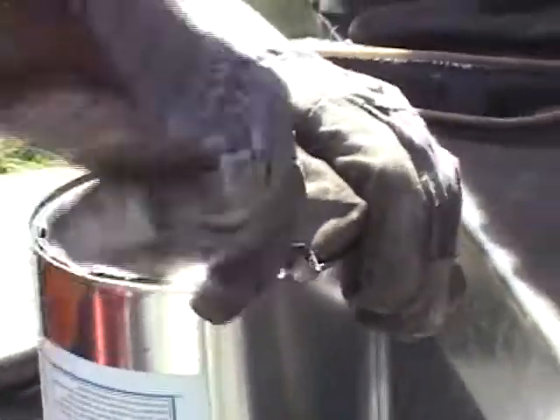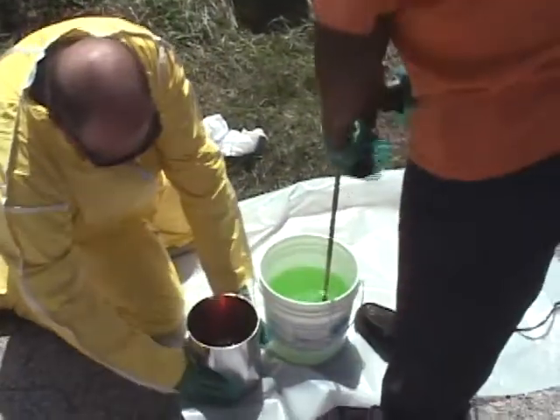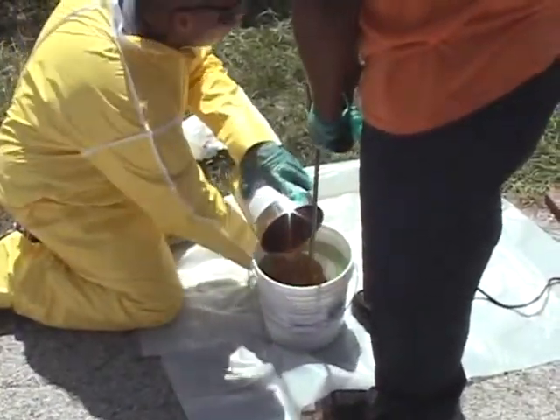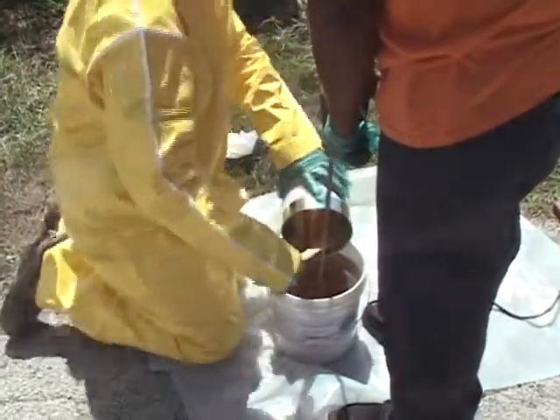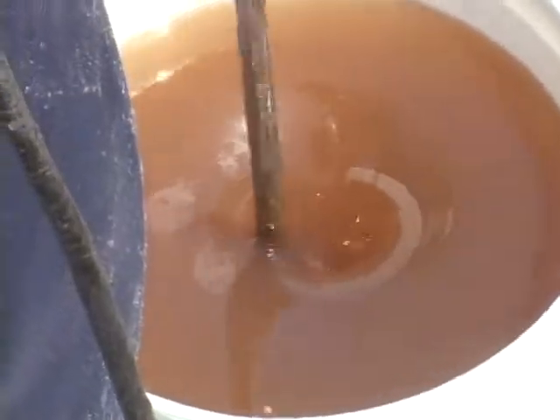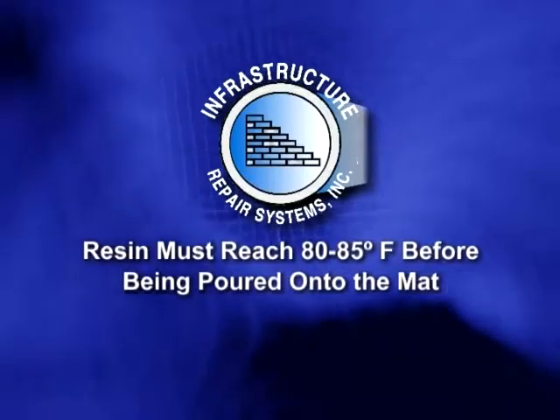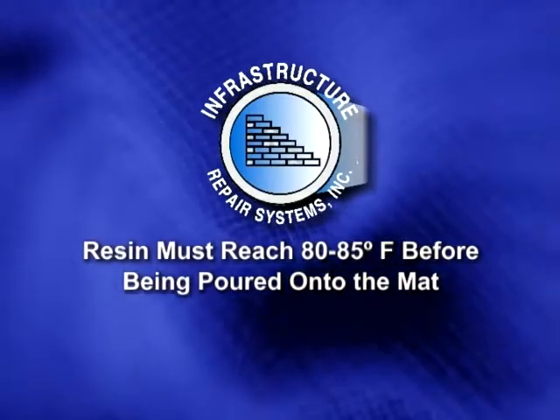Using a can opener, de-rim the B-side resin, the curing agent, and pour it into the A-side resin. Make sure you use all the B-side resin by scraping the inside of the can. Slowly and thoroughly mix the resins together for 2 minutes. After thoroughly mixing, check your resin temperatures. Let the resin reach 80 to 85 degrees before pouring it onto the repair mat.